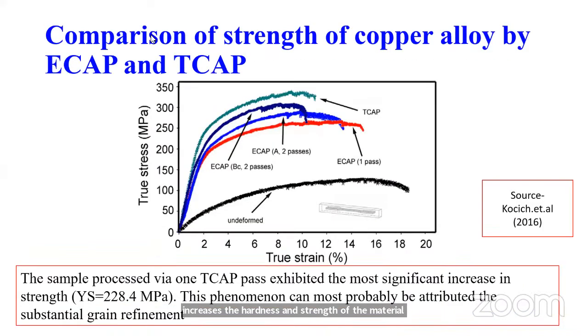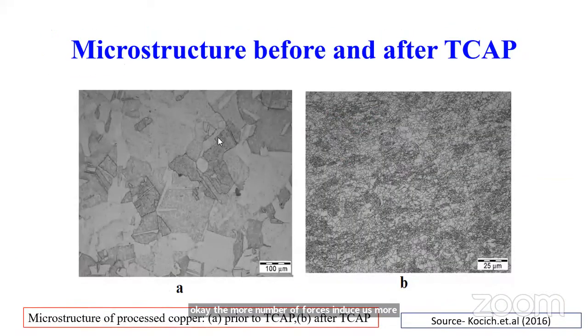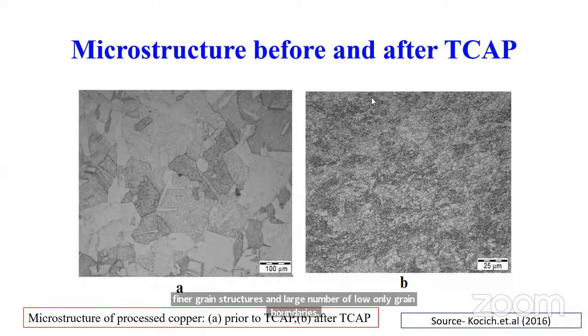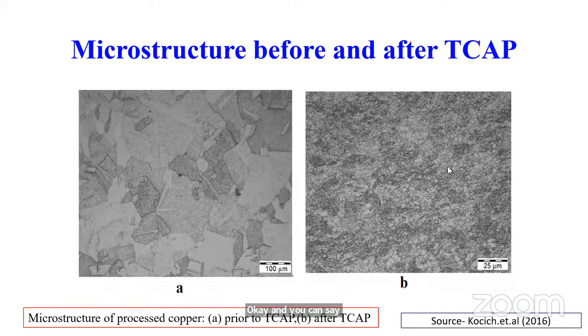You can see this is the comparison of strength of the copper alloy. The strength of TCAP processed material is high when compared to the ECAP passes. The more number of passes induces more strength and more hardness. These are the microstructures of the samples processed prior to TCAP and after TCAP. You can see the coarse grain structure is obtained in the sample before TCAP, which has less strength. You can see the material processed after TCAP, we have finer grain structures and a large number of low angle grain boundaries. And you can see that the material is refined, which improves the strength. At the same time, the hardness of the material is improved.